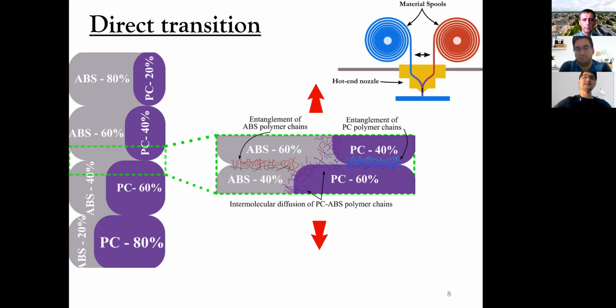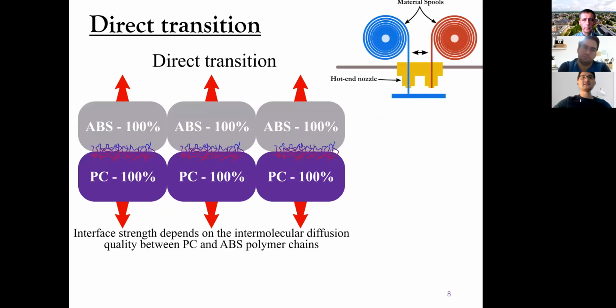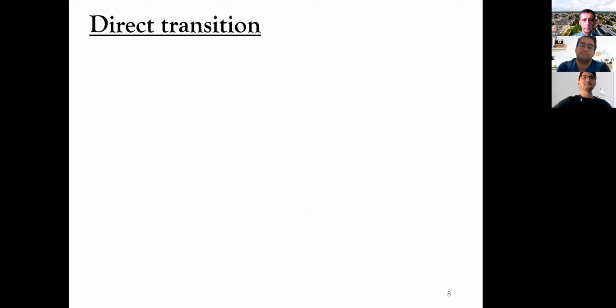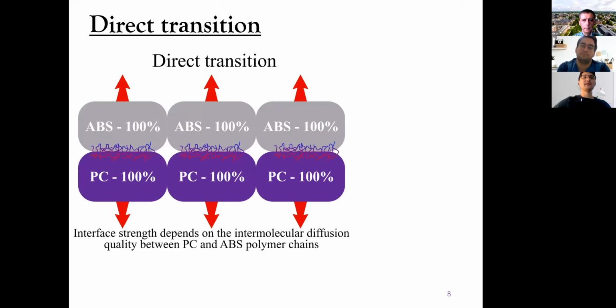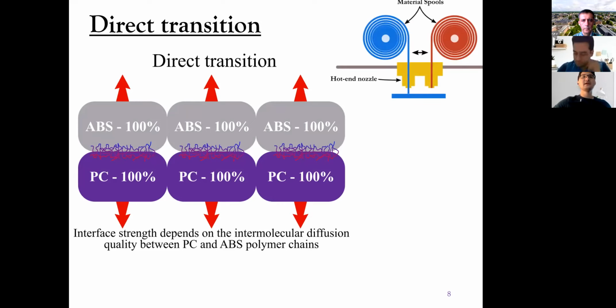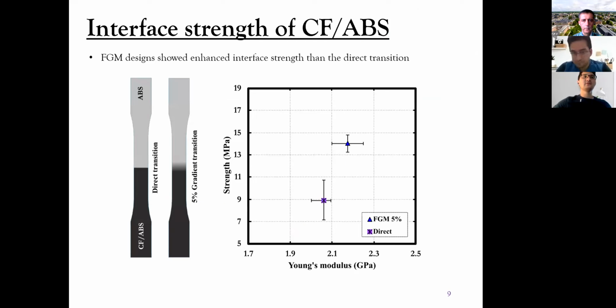And in direct transition, what we see over here, the transition starts after depositing one layer in one nozzle. Then we shift the nozzle, we start to deposit the second layer. This might reduce the intermolecular diffusion between polycarbonate and ABS materials. Therefore, in gradient transition, we experience better diffusion between materials, and also the gradual change of material properties helps to reduce the stress concentrations. Okay, let's take a look at the interface strengths of similar material interface.